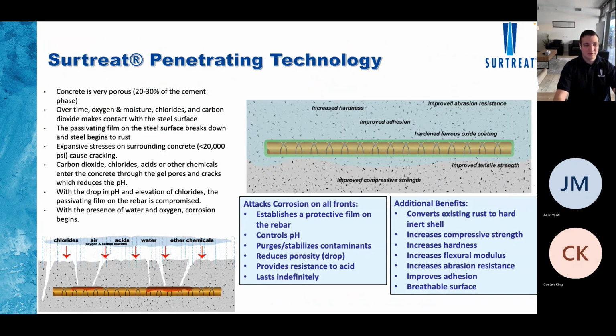So our technology, as you guys all know, concrete is very porous, which means that chlorides, air, acids, water, other chemicals are going to be able to permeate through the gel pores, through the microcracks, all the way to the rebar. They're going to settle in the rebar, and they're going to settle around the rebar, which is going to cause the pH to drop. Once the pH drops, you lose that passivating film on the rebar that's protecting it from corrosion, and it starts to deteriorate. The environment around the rebar starts to deteriorate. The corrosion starts setting in, it starts delaminating that concrete. Eventually, you're going to have those big spalls, those big delaminations.